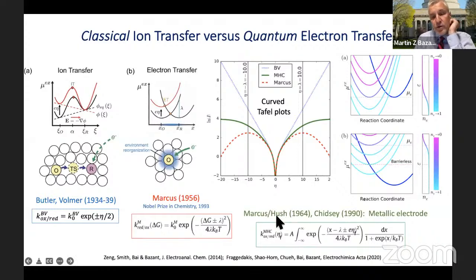And subsequent work by Marcus and also experimental observation by Chidsey in 1990 verified that in the case of electrodes, you have to basically take this Marcus rate and integrate over the band structure of the electrode, so the different types of energies available, and also the Fermi distribution, just saying how all electrons are actually distributed in that system.